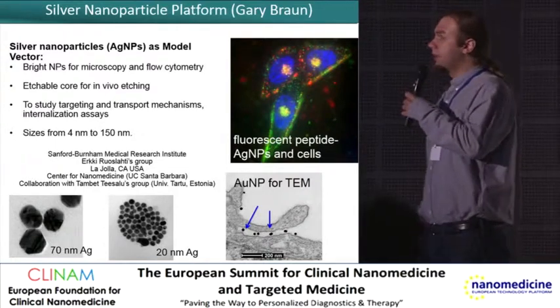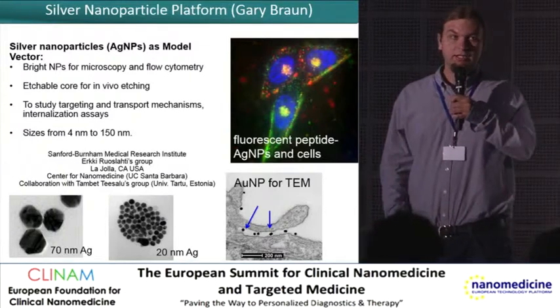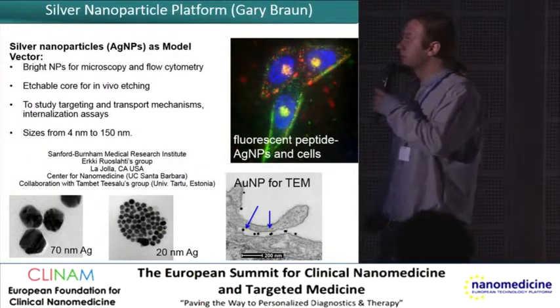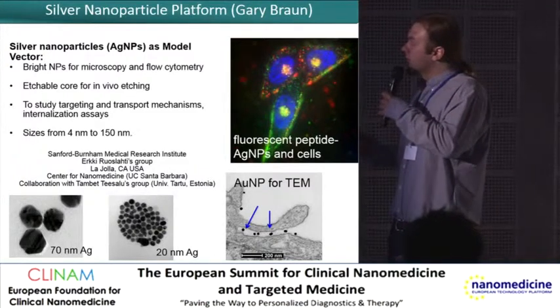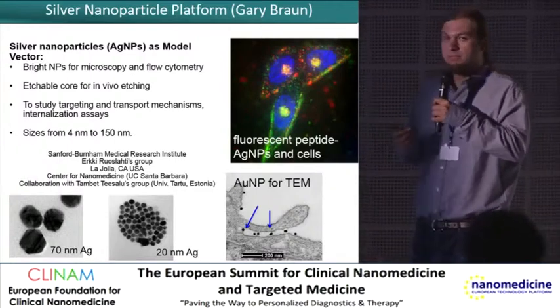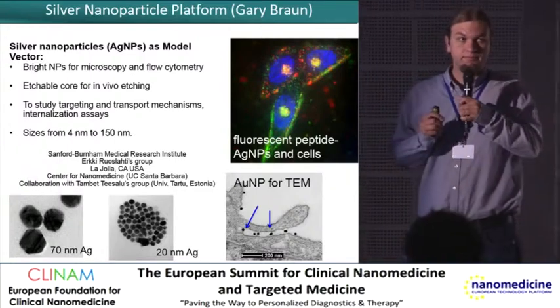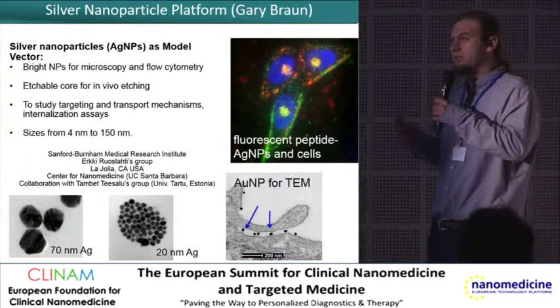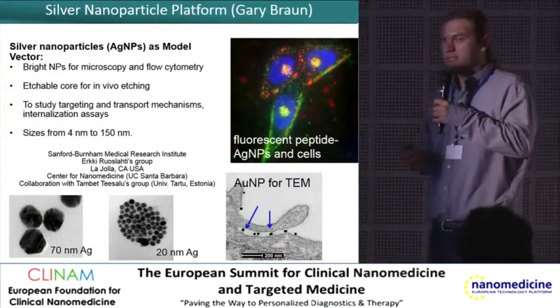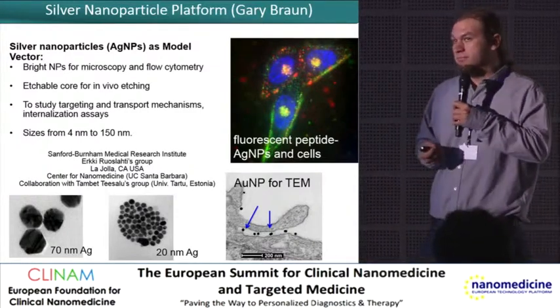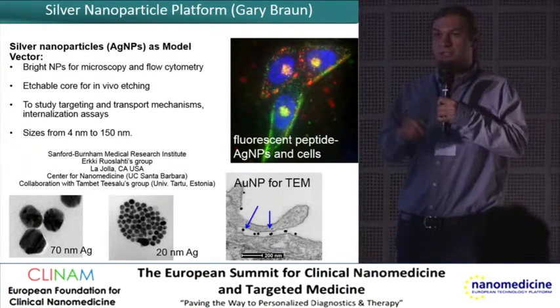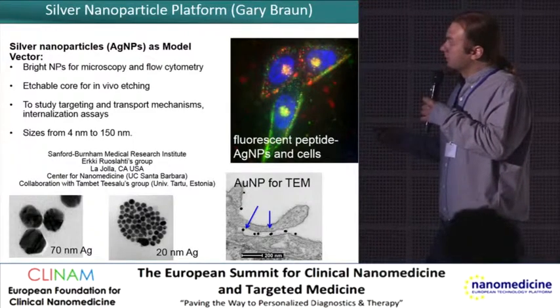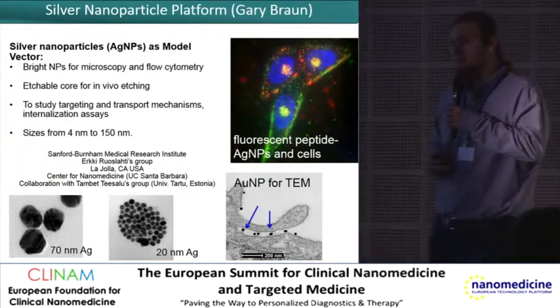Hello everyone. What I study is targeting of nanoparticles using peptides developed in the Ruoslahti lab at Sanford Burnham Medical Research Institute, located in San Diego, California. The core of the particle we use is silver, which enables a simple, bright tracking modality using fluorescent dyes attached to the surface. The silver enhances their fluorescence and we can use single particle tracing to watch internalization occur into tumor cells in vitro.